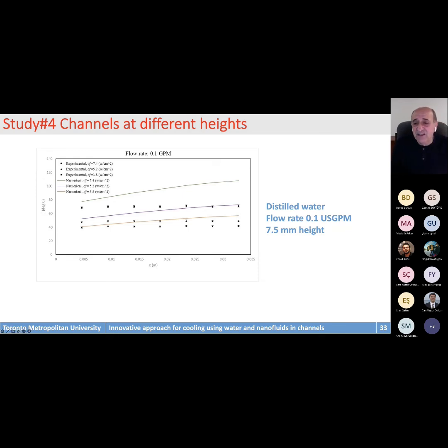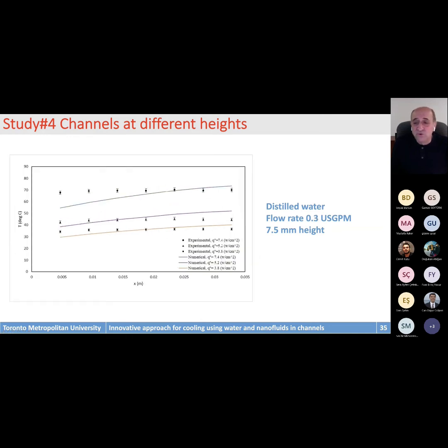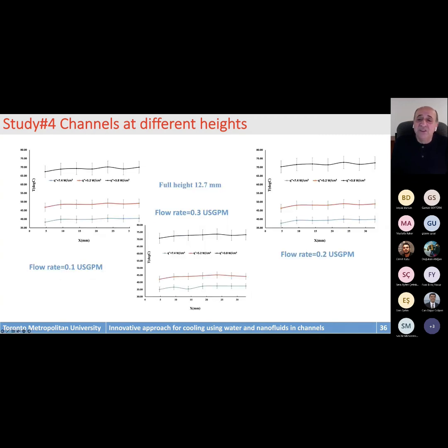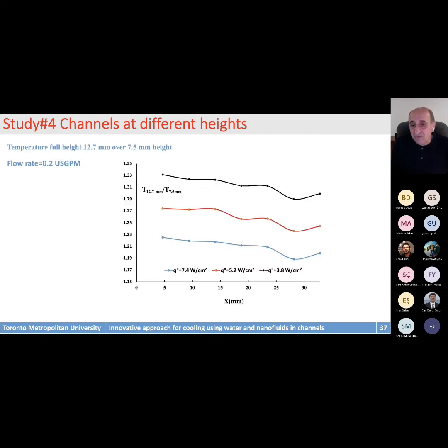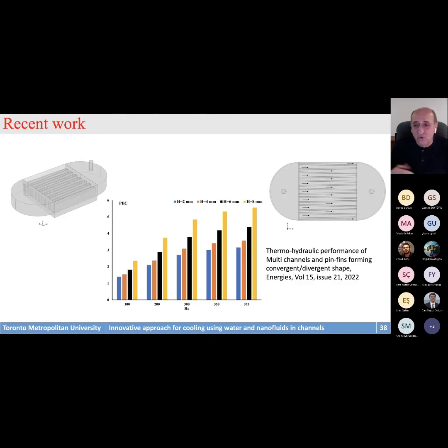We are still investigating. So we did the study for low flow rate, 0.1 US gallon per minute and 7.5 millimeter height. And then we increased the flow rate to 0.2 to 0.3. And then what we did, we tried to do it as well for full height, 12.7 millimeter and different flow rates. And we have kind of agreement between experimental and numerical. And when you look at the temperature between the 12.7 millimeter and the 7.5 millimeter, we notice that at 7.5 millimeter, the performance is slightly better due to this mixing. But again, this has to be checked very carefully before we come up with a final conclusion for it.